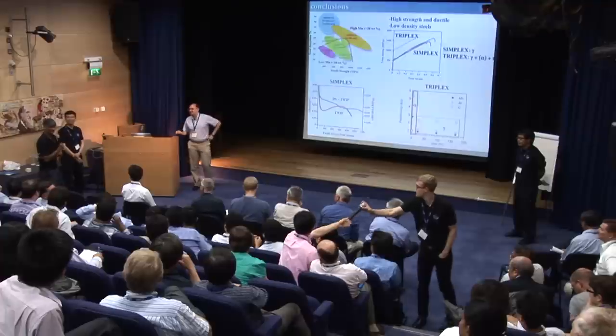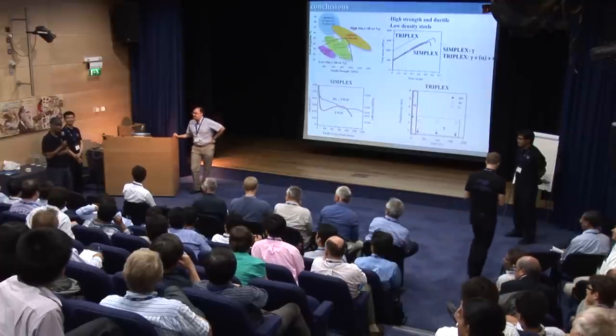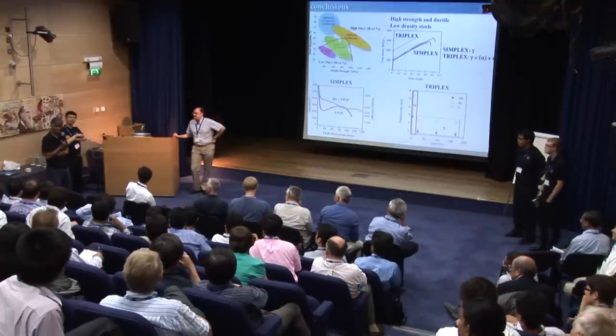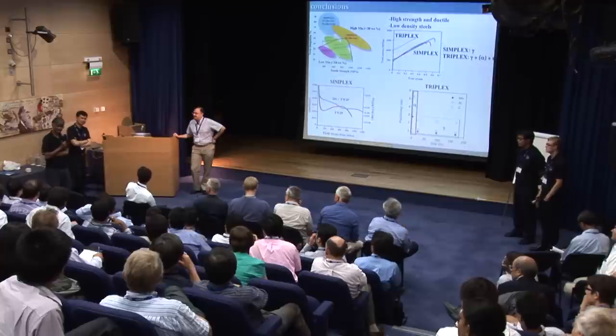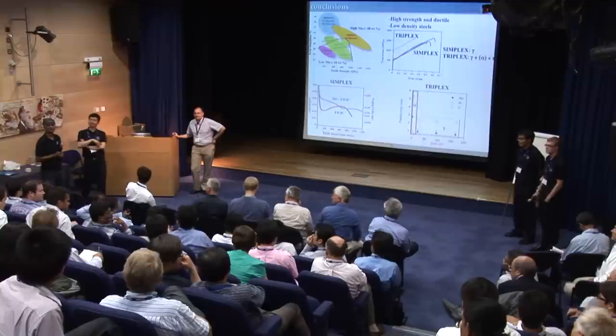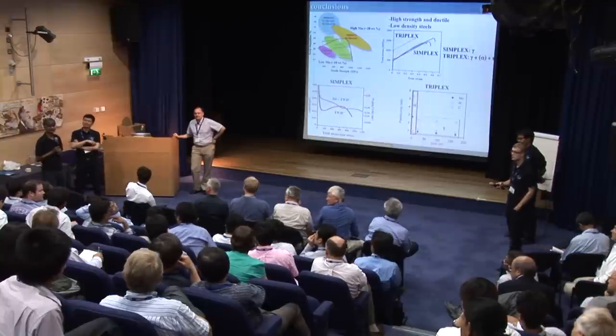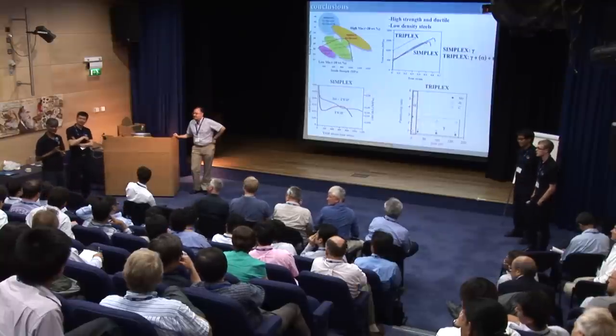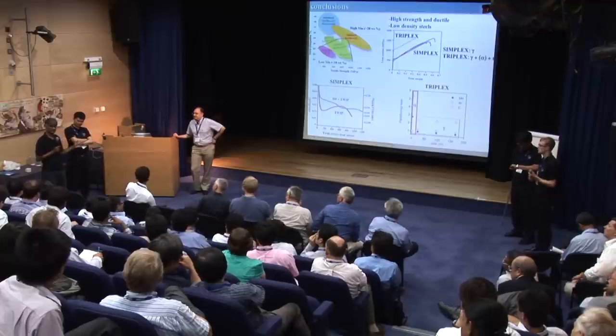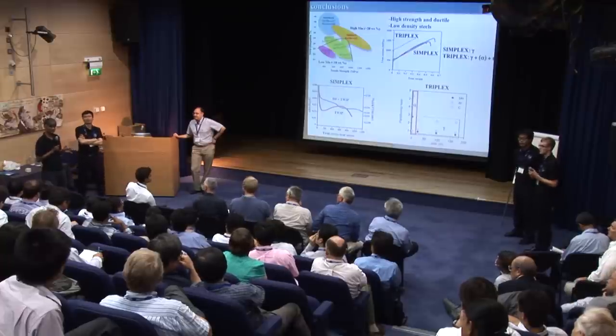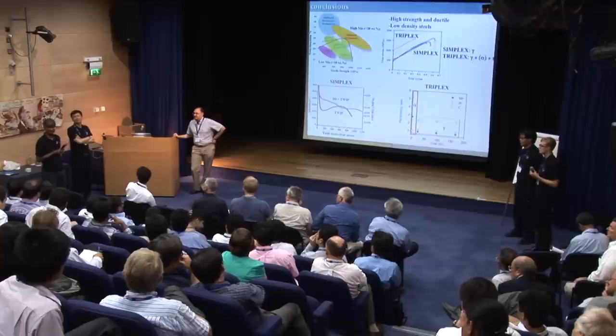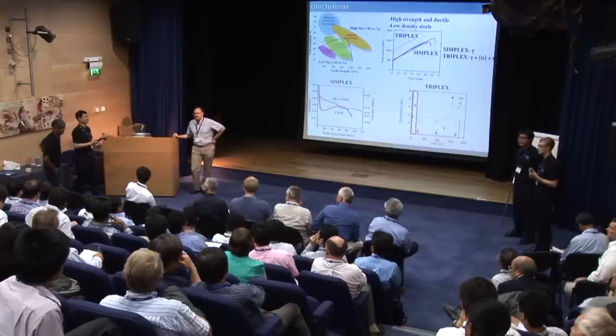The answer is yes, you can, because if you reduce the density by 10%, there is no aluminum alloy in the world which can compete on specific strength for automotive applications. If you're talking about strength-to-weight ratio, correct. That's exactly what I said: if you can reduce it by 10%, there is no aluminum alloy in the world which can compete with steel. Here we can go up to a yield strength of 1 gigapascal. You can tune the size of the carbide distribution, and it's pretty ductile.